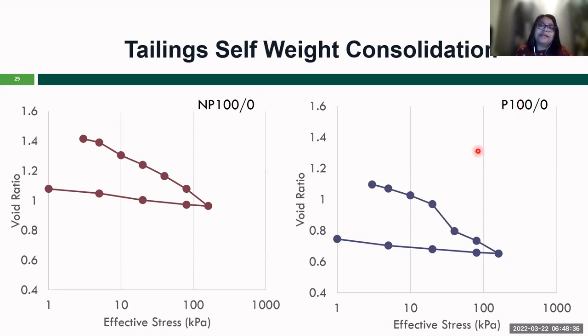So the polymer treated sample showed higher dewaterability from the data points, as you can see from these two diagrams. And we used two different densities for this material. So the initial packing density for non-polymer was 1.3 gram per cubic centimeter, gram per cc. And for the polymer treated one, it was 1.5 gram per cc. So the take home message could be, for the material we have received from the TSRU unit, polymer treated, we saw the non-linear behavior. Again, it's referring to the residual hydrocarbon, which could be the reason that we see this kind of behavior. But in the literature, we have seen both linear and non-linear behavior for polymer treated materials. And that depends on the type of polymer, the concentration, and the type of test performed.